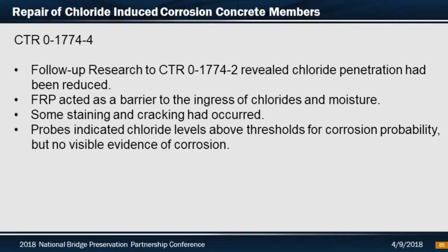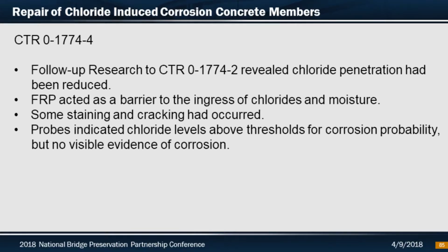So follow-up research was done, which came back out to the location and actually did some testing. It revealed the chloride penetration had been reduced, assuming then the FRP had acted as a barrier, which would stop the ingress of chlorides and moisture into the system. Like I mentioned, some staining and cracking had occurred. They also went back and investigated the probes, and the values coming off the chloride levels showed a high level of corrosion probability, but obviously since we covered it up, there was not really any evidence of corrosion, which would be the concern.